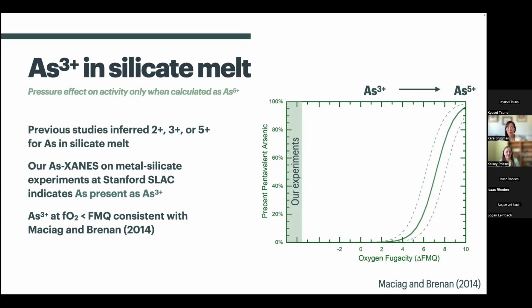But then the other thing about oxidation state to note is that with this KD approach that we're doing, when we take our metal silicate partitioning coefficients and ratio it to the D for iron, that's kind of a way, not necessarily to eliminate oxygen fugacity effects, but to try to normalize for them. So at the different oxygen fugacities, your D for iron is how we're calculating the oxygen fugacity relative to iron-wüstite. And when you normalize to that D for iron, it tries to normalize out that change in the oxygen fugacity and the behavior of iron in this system.